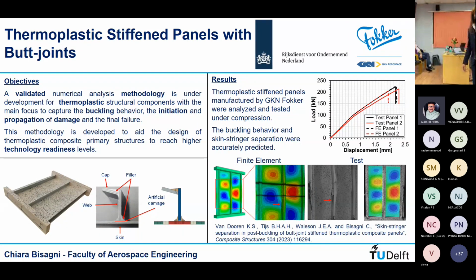And you see two different panels that we tested, nominally identical, but there was some imperfection, and so a little bit of difference between the two tests in the post-buckling field. But the correlation with the finite element analysis was pretty good.